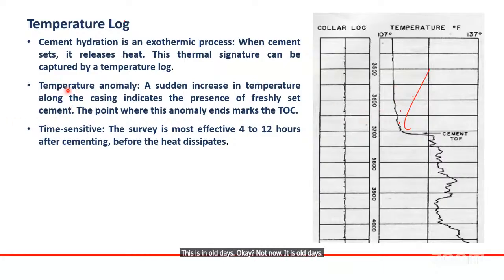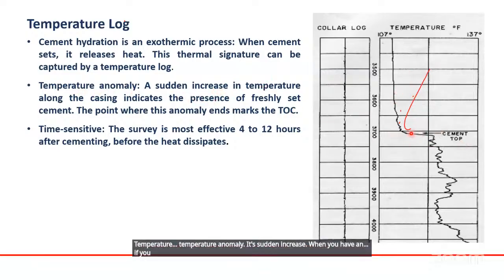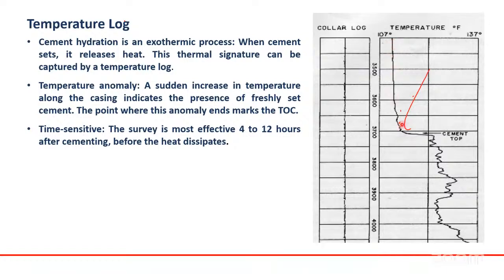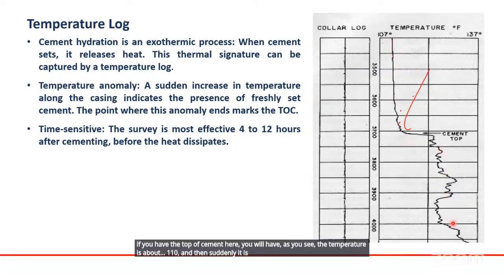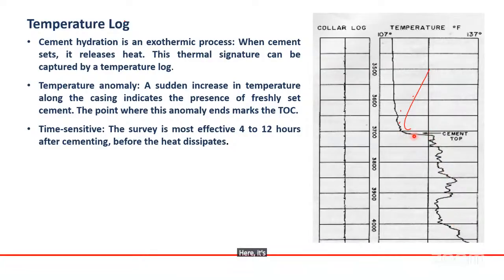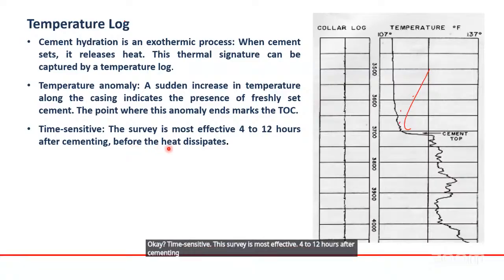Temperature anomaly: a sudden increase. If you have the top of cement here, as you see, the temperature is about 110, and then suddenly it is over 120 or 125. So the top of cement here is at 3710 or 3720. It is time sensitive. This survey is most effective 4 to 12 hours after cementing, before the heat dissipates.